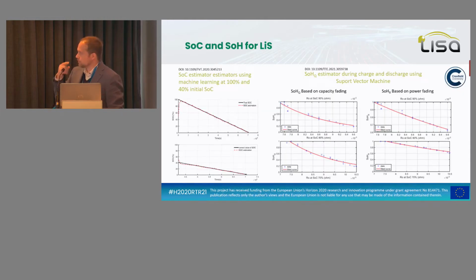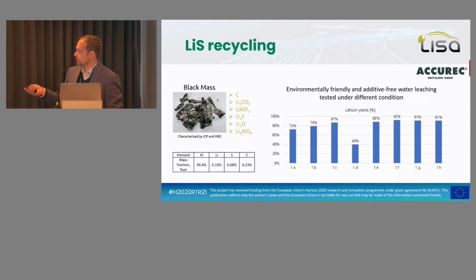This is the estimator. So for people that know, lithium sulfur is not working as lithium ion. This is not the same voltage. This is not the same behavior with the temperature, the C-rate, etc. So you have to build other algorithms to control the state of charge and, in this case, state of health also. Here, following 3 different methods. So all of this is published. This also aims to know how much you get from the first life to be able to use it after, no? So this is available.